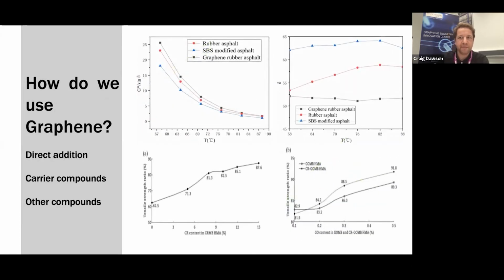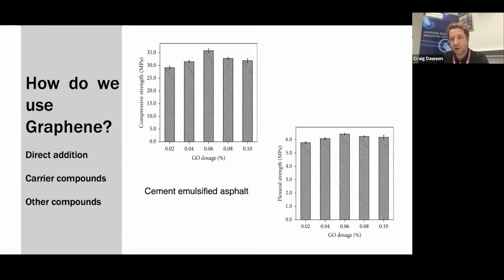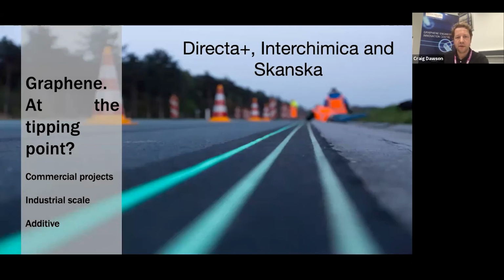So we can add graphene directly into a bitumen and then disperse that within an asphalt. But a lot of work's also been done in introducing graphene into a carrier system and then dispersing that into the bitumen and the asphalt. I'm going to concentrate probably more on these rubber ones as one of my case studies later on. Graphene within a rubber and then dispersed within an asphalt. And we can see with these graphs again these improvements in DSR results and in tensile strength. We've also dispersed graphene within these cement emulsified asphalts. And I'll go directly to these case studies now.